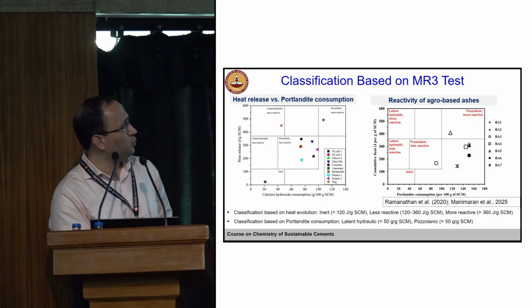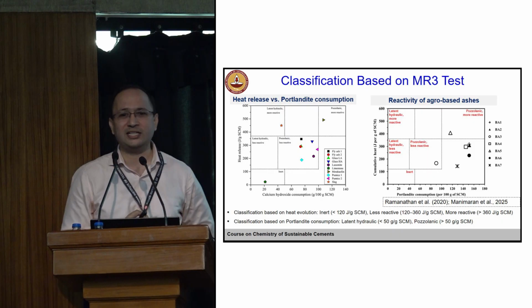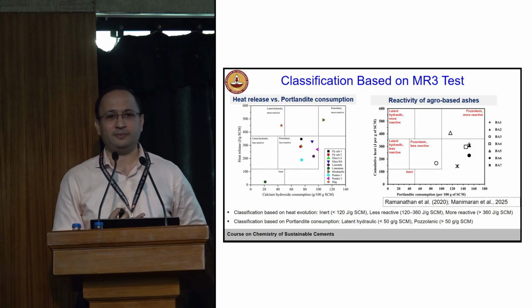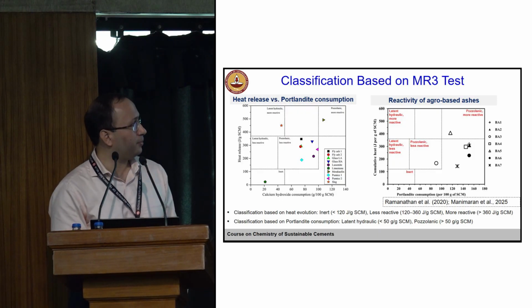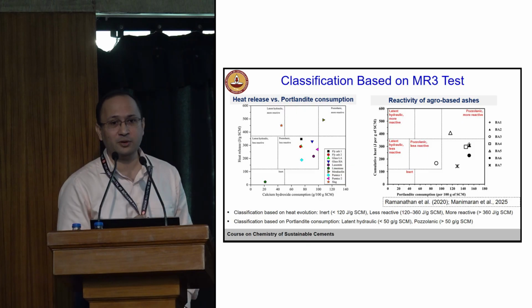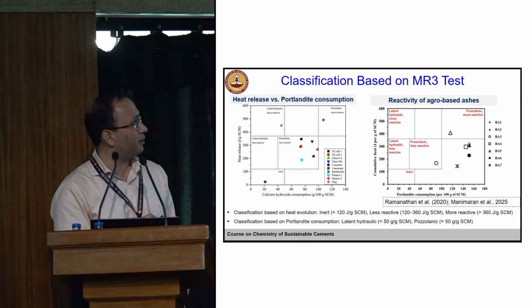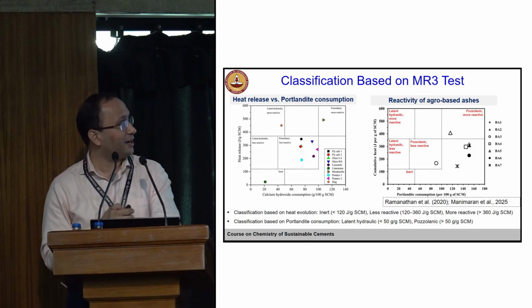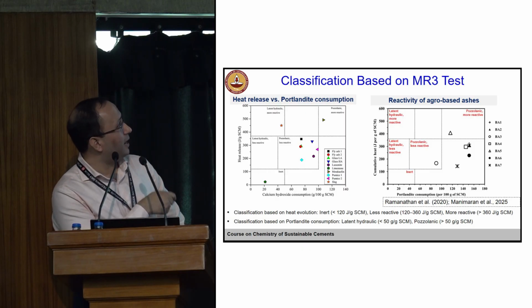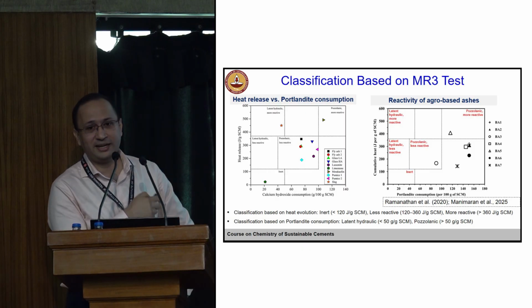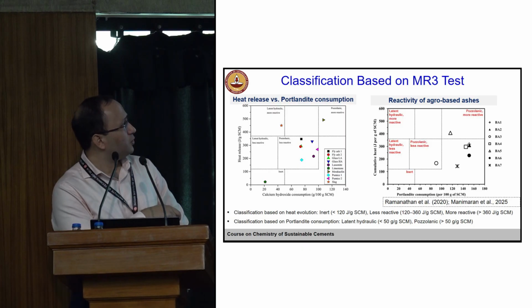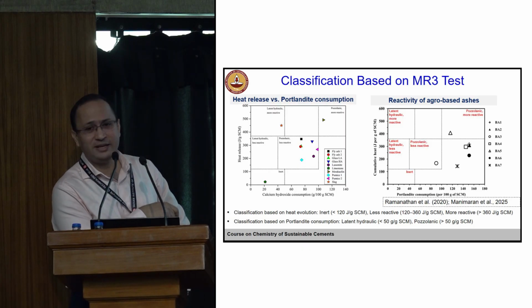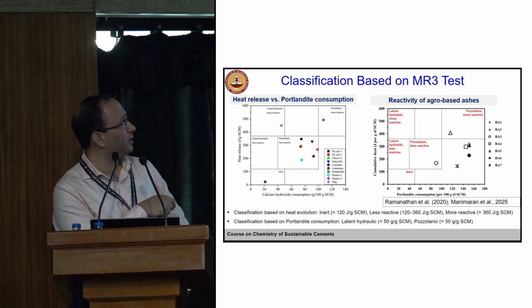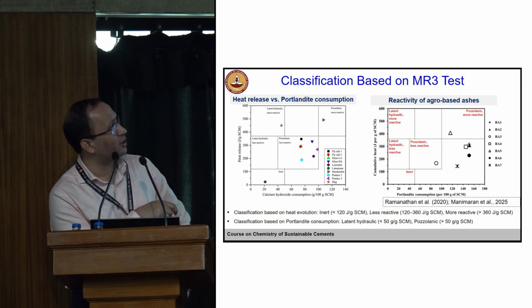So what you see on the x-axis is calcium hydroxide consumption, right? Again, why are we talking about calcium hydroxide consumption? Because of the pozzolanic reaction, right? So if there is a significant consumption of calcium hydroxide, that means it's a reactive system. And on the y-axis, you have heat release. Also, that tells you about the hydration. So inert will be somewhere here, very low consumption, low heat. And then you have some pozzolanic, less reactive system. You have pozzolanic, more reactive.